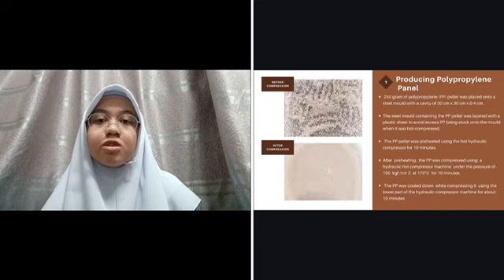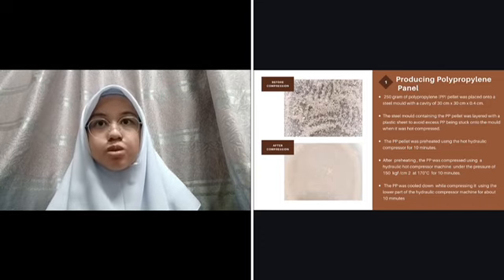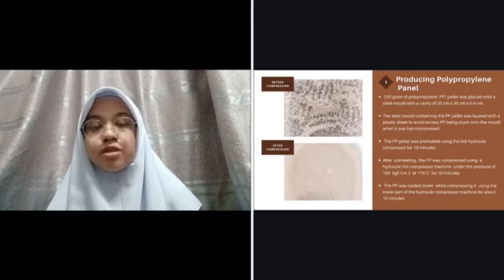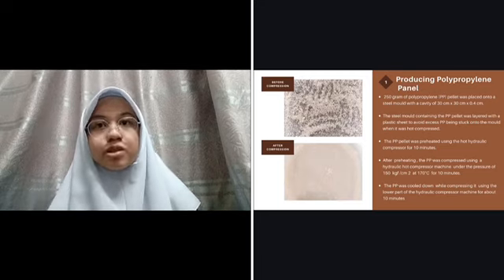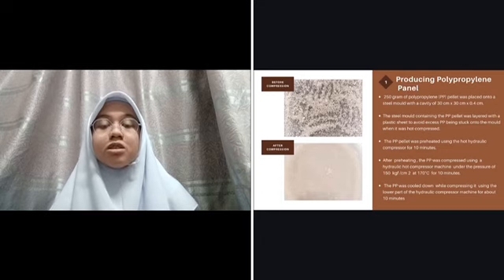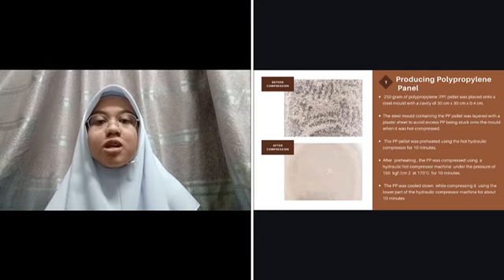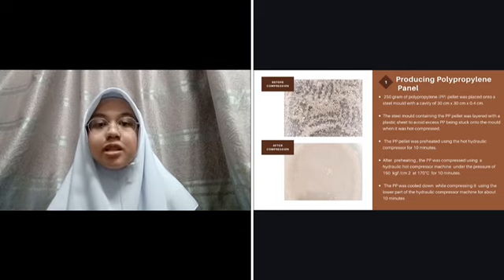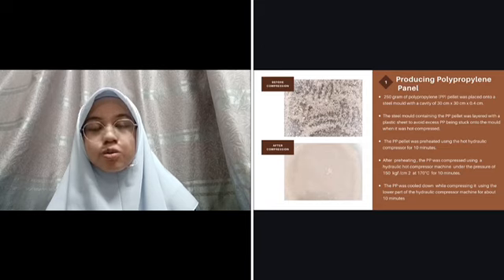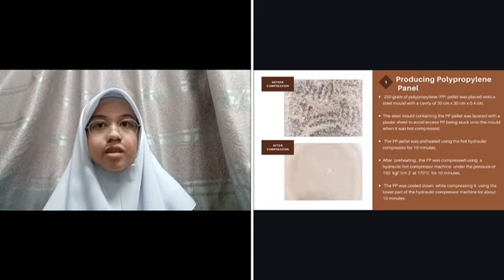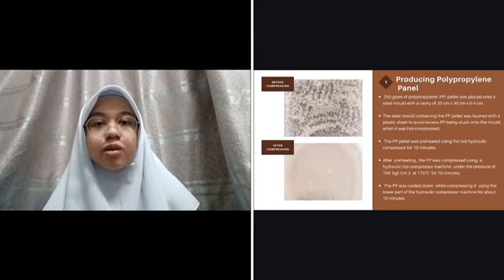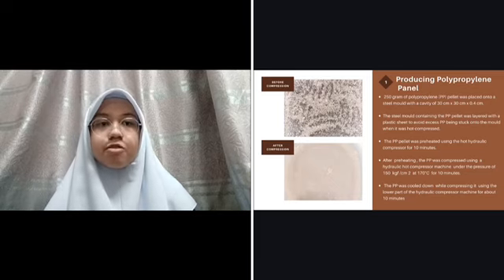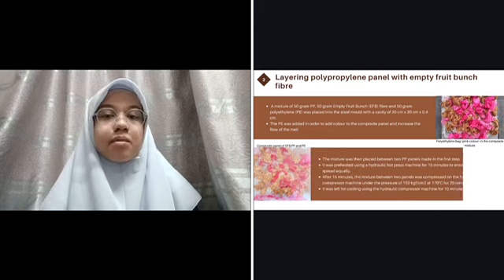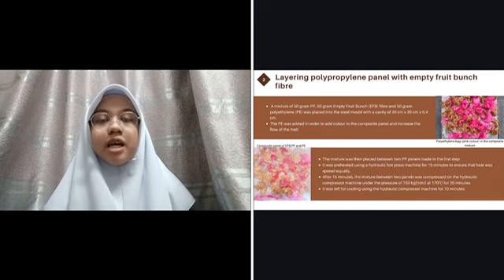And in order to avoid the polypropylene from sticking to the steel mold, we layered it with a plastic sheet. And after the preheating process was done, we compressed the polypropylene using the same hot hydraulic compressor machine under the pressure of 190 kg force per square centimeter for about 10 minutes. And the temperature was 170 degrees Celsius. And lastly, the polypropylene was cooled down using the lower part of the hydraulic compressor for about 10 minutes. The second step is to layer the polypropylene panel with the empty fruit bunch fiber.